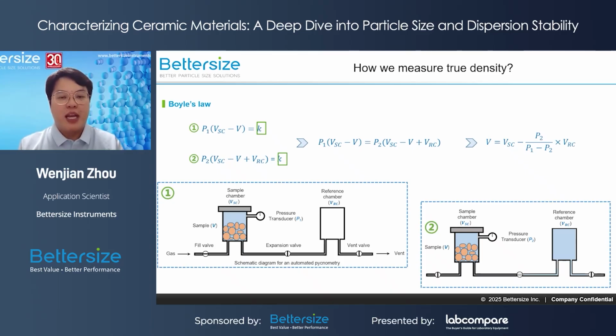By applying this law, let's see how a gas pycnometer calculates the true density. A typical gas pycnometer has a sample chamber, a reference chamber, a pressure transducer, and three main valves: the fill valve, expansion valve, and a vent valve. Imagine we are using a gas pycnometer now. We start the measurement by opening the lid and placing the sample in the sample chamber. Close the lid, keeping the expansion valve closed. Open the fill valve to allow a specific amount of gas to enter the sample chamber. Then close the fill valve. The pressure at this point is recorded as P1.